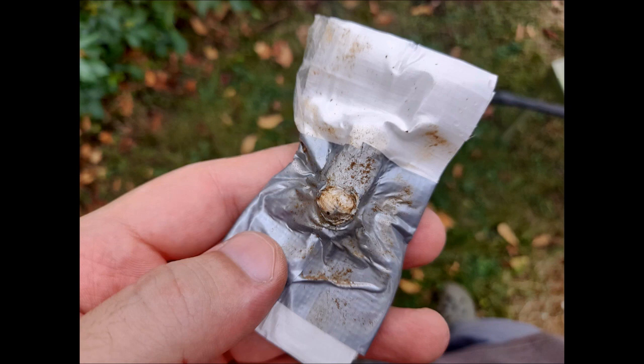It was actually enough to push the sample a bit into the mud that I used as a support to simulate a wearer, and it was even enough to burst open the duct tape on the back. And it is only with a slightly less than 20 joule projectile. Now imagine with something of multiple hundreds of joules like a pistol round. This type of BFD is totally unacceptable.